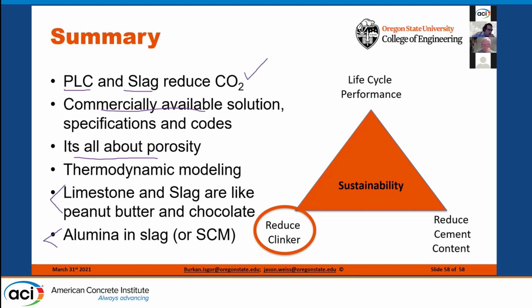Mahir asked a really good question that was, is this grade 100 or 120 slag? And I would say we get very similar performance from both of those. And there was actually a pretty good discussion yesterday with slag folks about really how much of a difference those grades are making. There's a little bit of a speed difference with the 120s, but the 100s work really, really well for what we're trying to do here.